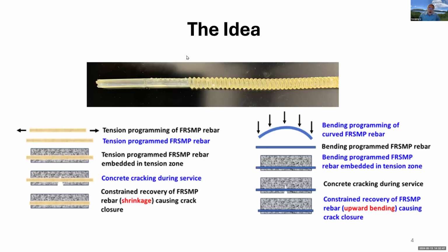You can see that the photo above is an FRP rebar using conventional polymer that we prepared in the lab. This is glass fiber reinforced. So the new idea is that, assuming you have this rebar, you do a tension programming, similar to pre-stressing in the concrete industry. After this pre-stretching, you put it into a concrete beam, and then this beam will be in service. Assuming during service, you create such a crack due to bending or other types of stress.